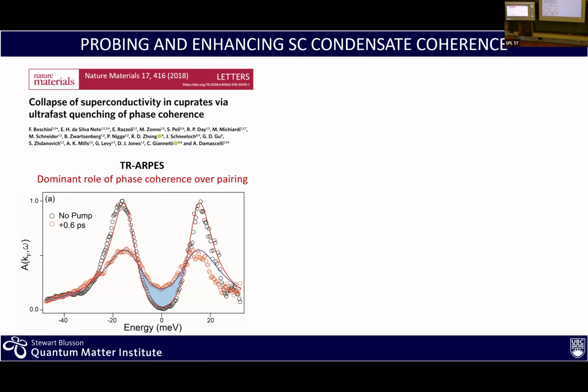And what we can conclude is that the peaks are not really moving, but really it's their width that gets broadened out. And so width means lifetime of excitation. So by pumping, we suppress superconductivity by killing the lifetime in the system. And so what we concluded from this work is that we quench superconductivity not by reducing the pairing, but by reducing the phase coherence of the overall condensate. So affecting the phase coherence versus the pairing strength.